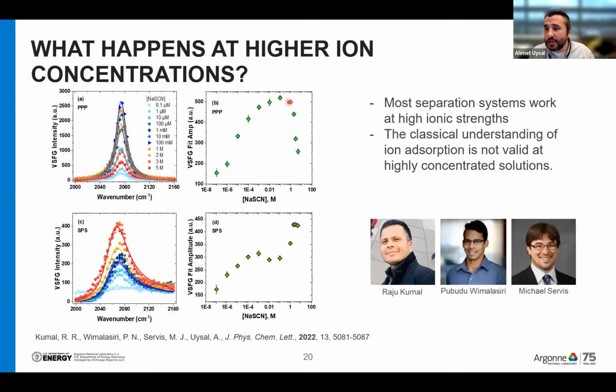After this saturation, what we see is the PPP signal starts going down, and the SPS signal goes up and then stabilizes again. This is very interesting. Again, the signal is not only proportional to the number density, but also to orientational ordering. And if you have two thiocyanate ions oppositely oriented, their signals will cancel each other. Is that what is really happening with this PPP signal?